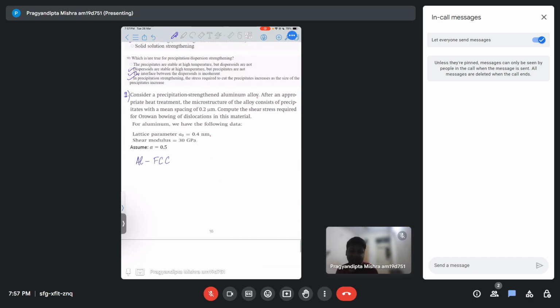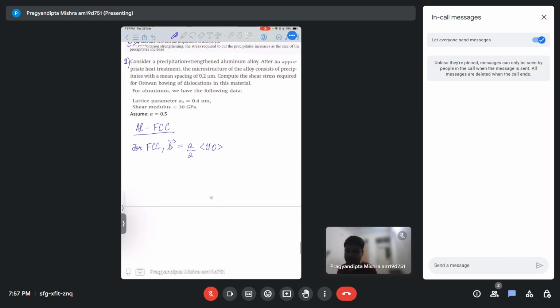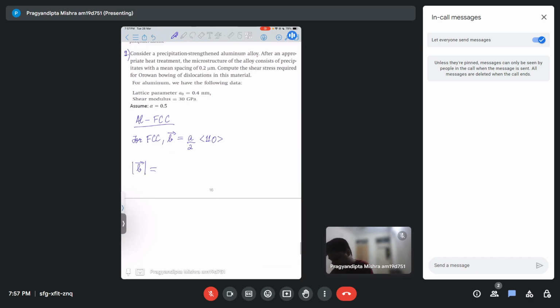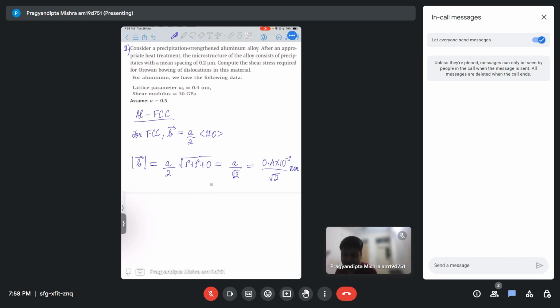Aluminium is FCC, right? So for FCC we have Burgers vector to be a by 2 <110>, right? So the mod of b, the b that we need for the equation, will be equal to a by 2 root of 1 squared plus 1 squared plus 0 squared. So that will be a by root 2. Now a naught is given as 0.4 nanometer. So 0.4 into 10 power minus 9 divided by root 2 is my b. So if I calculate this, b will be equal to,